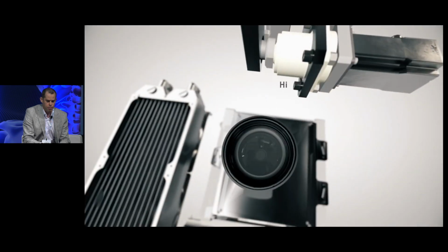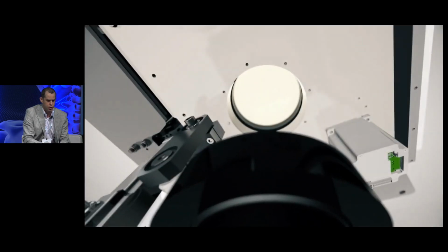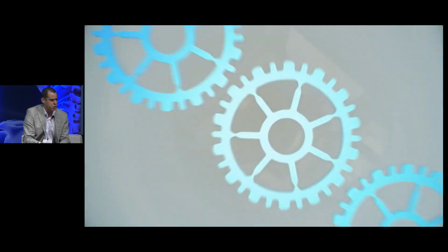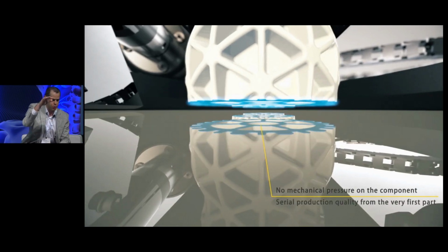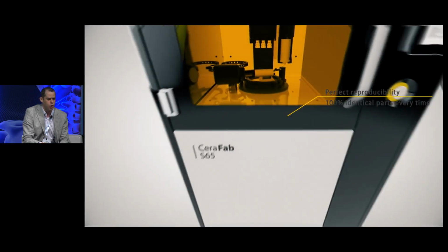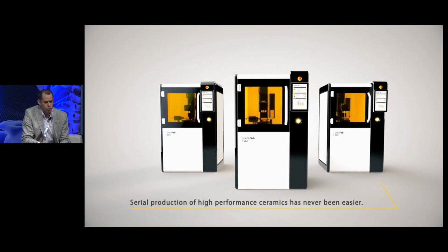So beneath that vat, once the slurry is spread through, you have a very complex optical system, which allows for blue light to shine through that optical system and cast a CAD file layer by layer. And that blue light clears each individual section of the device. So ultimately, one can create a full 3D print with the build plate dipping in and out of the vat. As far as speed, we're talking about 150 layers can be printed per hour, each layer as fine as 10 microns.